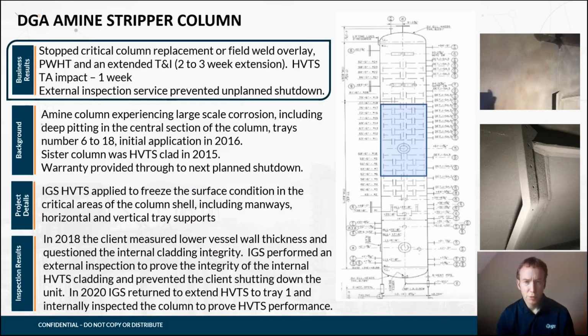This next example, similar to the first one, it's a section of the column where you typically see aggressive pitting corrosion taking place. This is a DGA amine column in this case. What's different about this example, or slightly different story, is the fact that the client, during the operation of the vessel, believed that he had continuing internal corrosion taking place. So he took some NDT measurements externally and believed that he was seeing metal loss. So what IGS can do with the internal thermal spray is we can use external inspection techniques to pick up that the internal cladding is still in situ and still operating as required.